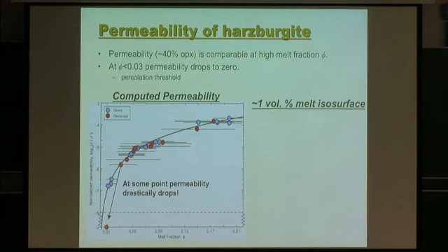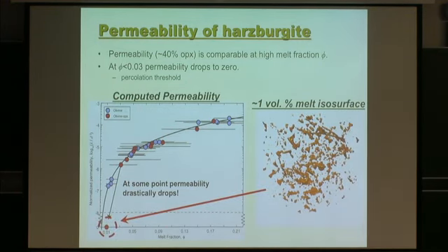But below that, we actually find, for example, one of these that's around 1% of overall melt. We calculated permeability and it came out 0, because if you look at it, there's no thoroughgoing percolation network, right? So essentially the melt is being isolated, all right?